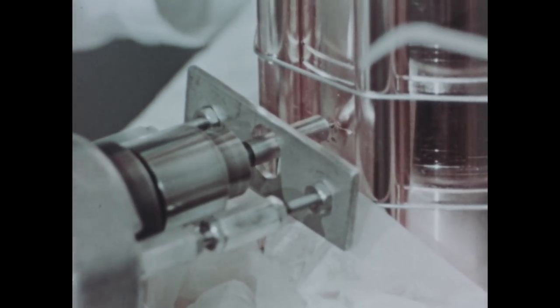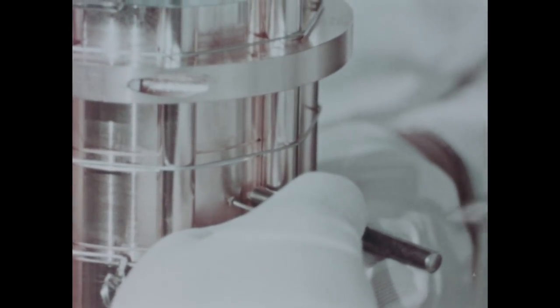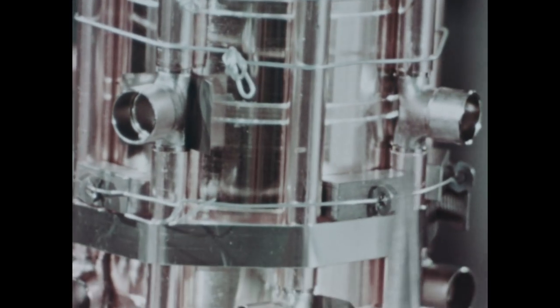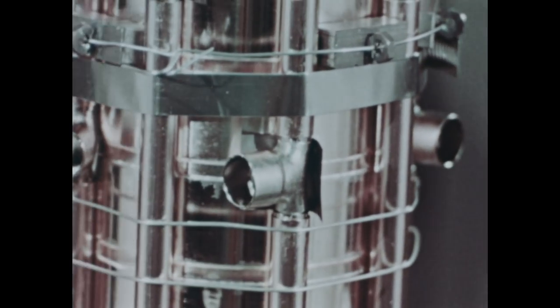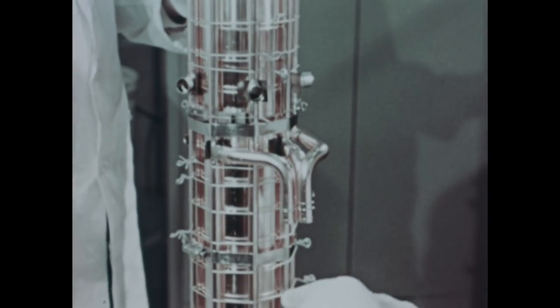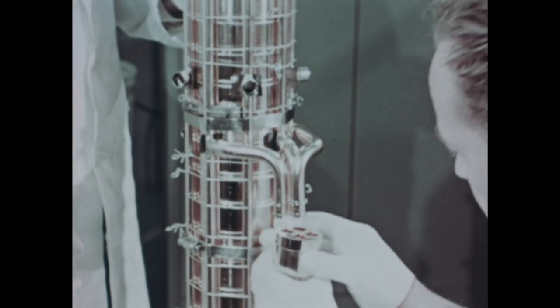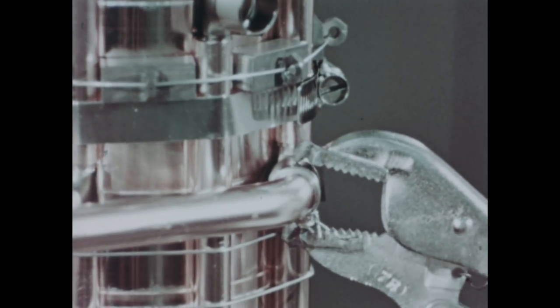Additional holes are drilled for thermocouple wires, which are inserted with alloy and will be brazed into the pipe at the same time the water jacket is brazed. To enhance temperature uniformity in operation, sheets of stainless steel are placed under the nickel-plated T's to prevent them from being brazed to the pipe. Feed tubes are installed, as are the inlet and outlet manifold blocks. The tubes are gently crimped to hold them in place. The tie wires are double-checked and tightened. The entire unit is carefully examined and the assembly is ready to be brazed.